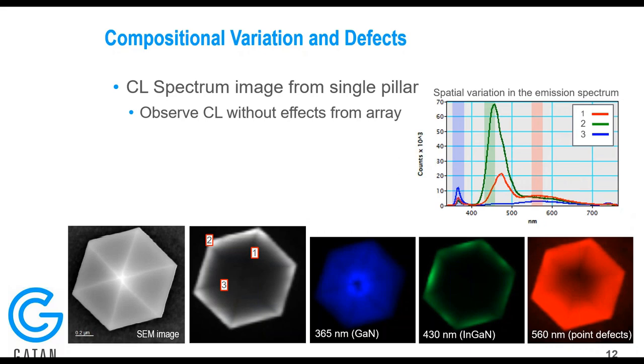The one at 365 is the native gallium nitride band gap. At 430, we can see the indium gallium nitride band gap. And at 560, we can see the point defect band. So this is just giving you an idea of where the emission is coming from across the surface of the sample.